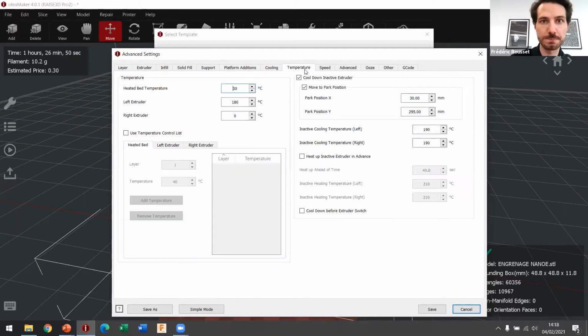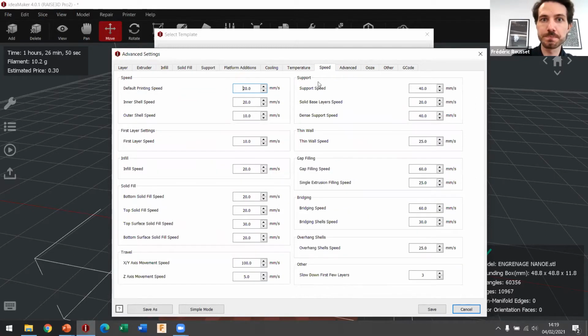This is important. For the extruder temperature, you are at 180 degrees, so this is below 200 degrees, and most printers can do it quite easily. For the heated bed temperature, it is at 30 degrees. It is very low, which is very good because some printers cannot go over 80 or 100 degrees on the bed temperature. So this is very important as well.